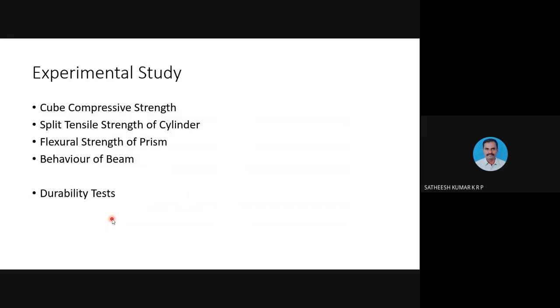So the experimental studies which we were able to complete are the cube compressive strength, split tensile strength, and flexural strength of prisms, and we were also able to test some specimens of beams. The cube compressive strength was done for all 4 combinations of the alkaline solutions. We tried sodium hydroxide with sodium silicate, sodium hydroxide with potassium silicate, potassium hydroxide with sodium silicate, and potassium hydroxide with potassium silicate. All 4 combinations were tested with different molarities of the solutions, from 6 molar until 14 molar.